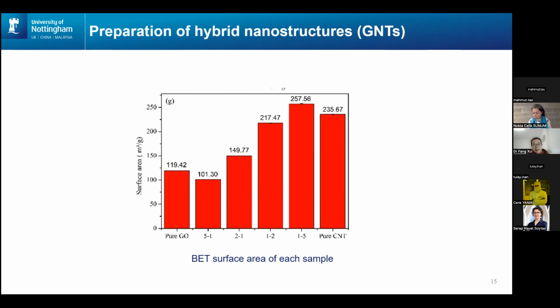But if we keep adding carbon nanotubes, we can see the surface area increasing and reach 257 square meters per gram. But if we remove graphene oxide, it will drop again.